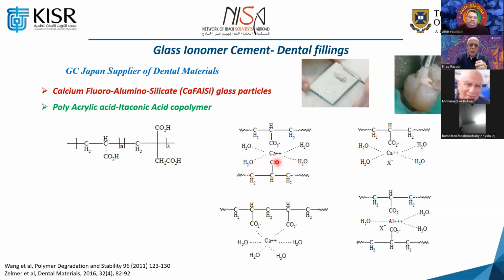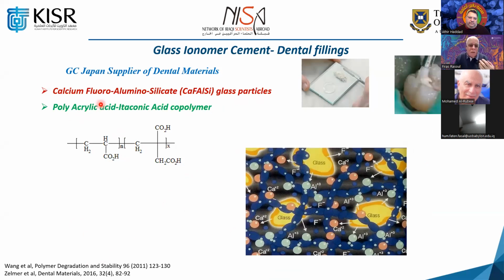That's why this salt bridge is very, very susceptible to acids. If somebody drinks a lot of Pepsi Cola and Coca-Cola and has this filling in his teeth, then you probably tend to break this bond and make it weaker and weaker. And of course, the advantage of this type of glass particle in this application is that you have a fluoride. So when you use this type of filling, especially in children, after curing the material starts continuously introducing fluorides, leaching from that matrix because of this glass particle. So it has a useful application. Besides being a temporary filling, it is also producing fluoride, which is essential for the teeth. So this is really one of the useful features of this material.